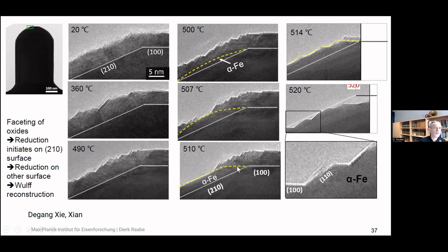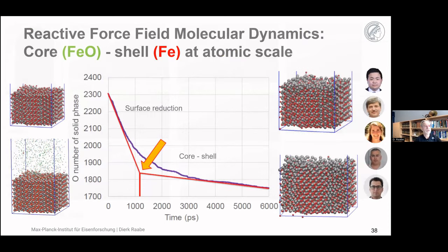And by that, we learn about the role of the crystallographic faceting, because all the transport and reduction kinetics and the catalysis of the H2 splitting depend, of course, on the type of oxide and facet and on these atomic details. So in principle, you must always place that back in a Wulff construction. We also do a lot of DFT and MD together with our theory colleagues. And you see also here a classical reactive force field molecular dynamics simulation, which is not so difficult to run. You can do that in LAMMPS and the potentials are published, so they enable simple chemical reactions.